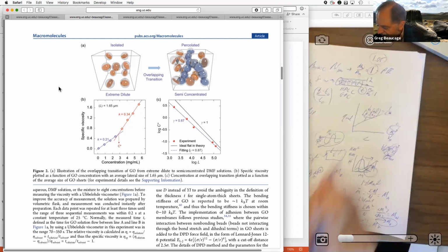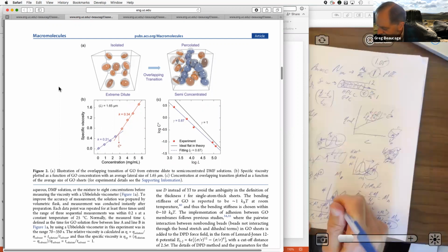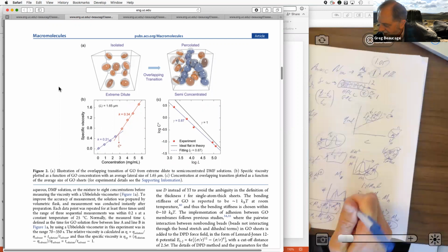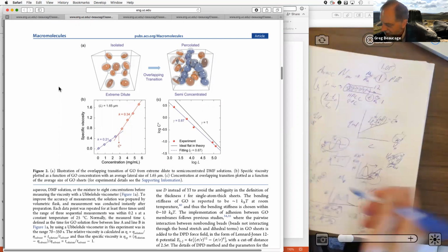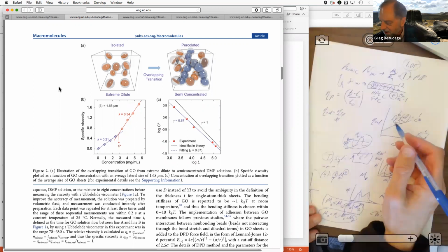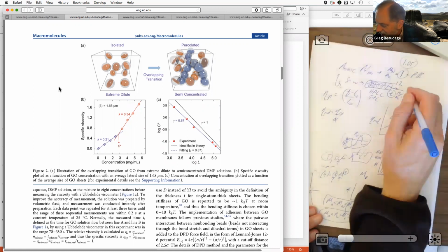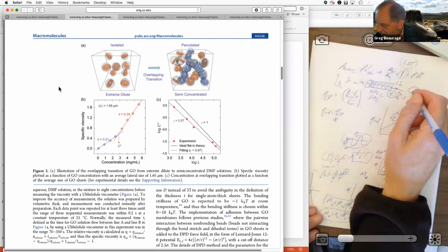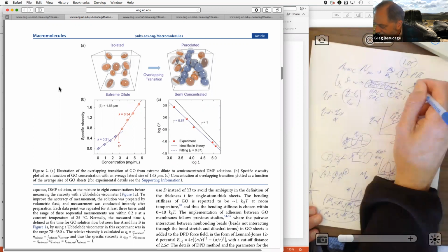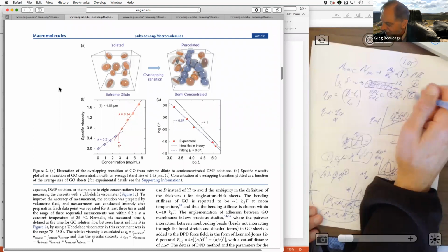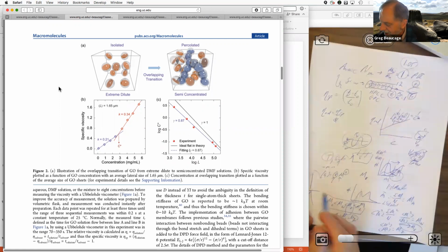And each of those, if the flow is slow enough, is monodisperse, which means that any method to measure the molecular weight will give you the same molecular weight. Meaning you can run that through a viscometer. So at the end of that, you can run it through a viscometer. One channel would be the solvent, and the other channel would be the solution. And then from the comparison of those two flow times, since it's monodisperse, you can just get the molecular weight from that using the Mark-Houwink equation.